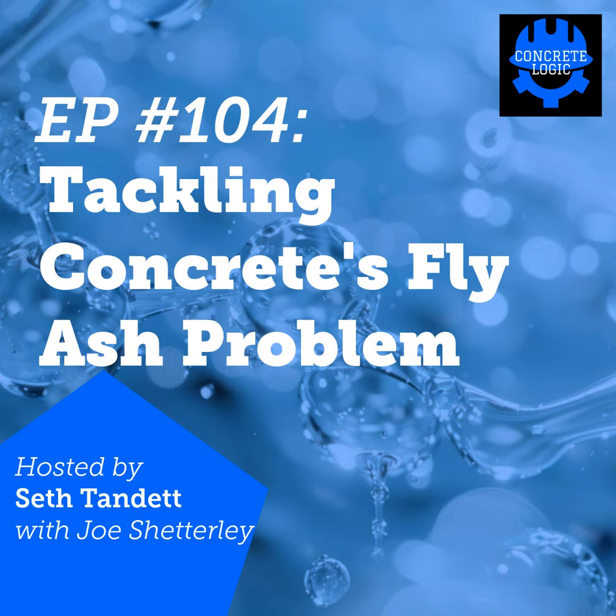Well, we did the first pour and we go down there and there was this massive, random cracking. It's like, oh my gosh, what happened? Well, we start going back. To our earlier conversation, water demand wasn't met. It was too dry. Second, the internal cure did its job, but the water wasn't distributed enough in that mix. The fly ash wasn't able to wet out, so it robbed more water. And then the cement wasn't wetting out because of the fineness of it. So they had this lack of water going on.